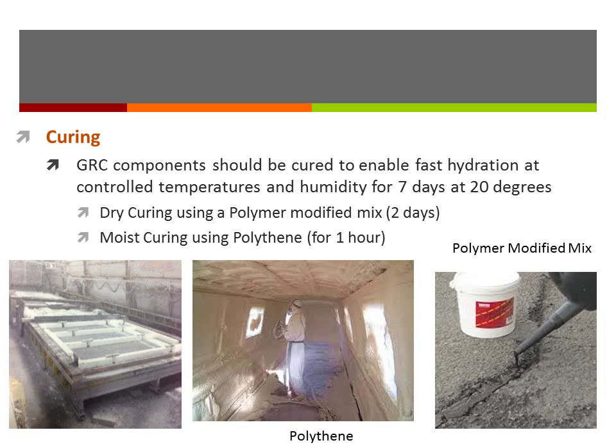The curing process: GRC components should be cured to enable fast hydration at controlled temperatures and humidity for seven days at 20 degrees. Dry curing using a polymer modified mix takes two days, and moist curing using polythene takes one hour.